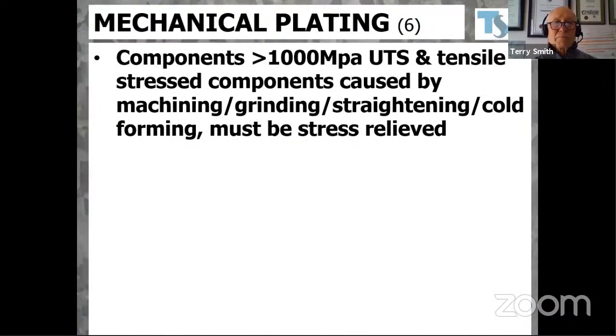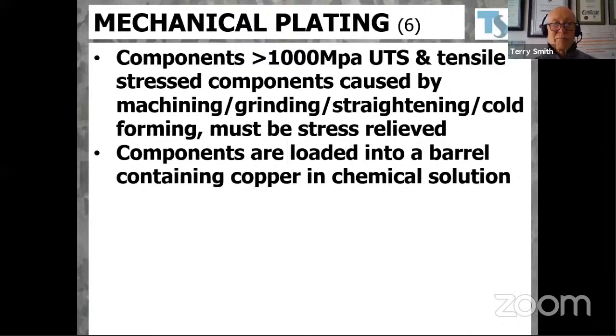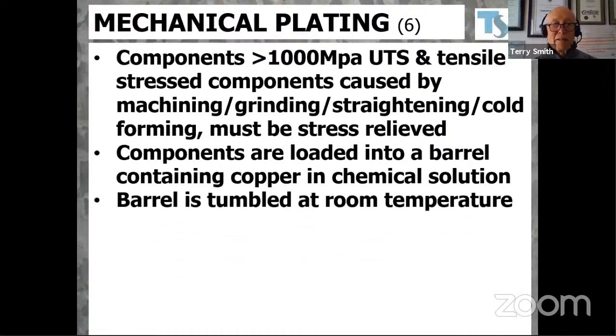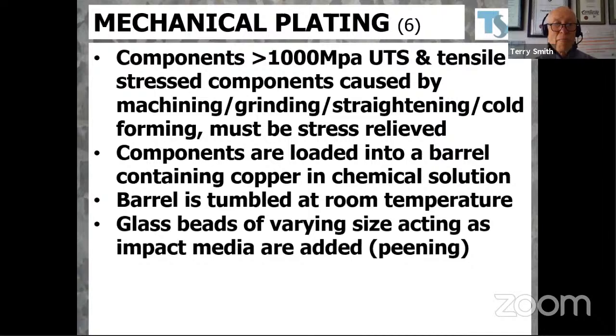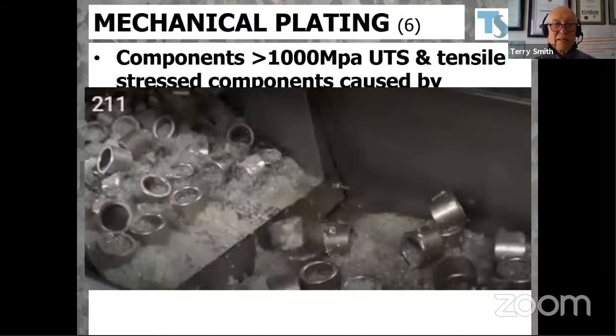Mechanical plating: for components greater than 1,000 MPa ultimate tensile strength, and tensile stress components caused by machining, grinding, straightening, or cold forming must be stress relieved prior to the process. Components are loaded into a rubber-lined barrel containing copper in a chemical solution. The barrel is tumbled at room temperature. Glass beads of varying size act as the impact media, and sometimes this is also called peen plating. There you can see the glass beads inside there.